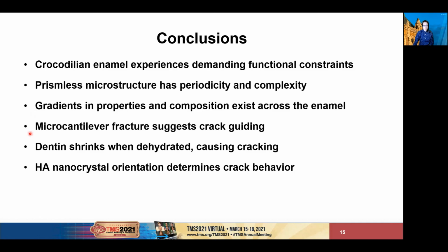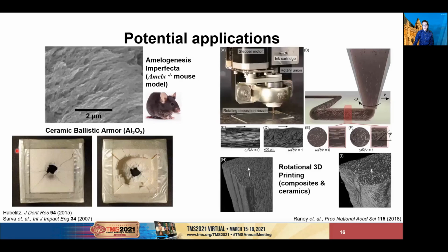The prismless microstructure is found to be capable of guiding cracks, as evidenced by both the fracture surfaces of microcantilevers and the cracks caused by dehydration. Some potential areas that we think these findings will be useful for include amelogenesis imperfecta research and the design of impact-resistant ceramic armor through the use of rotational 3D printing.